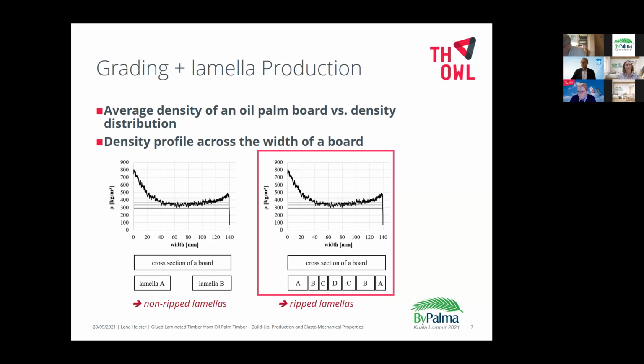trunk. In comparison to the conventional way of lamella production, you can see on the right the same density profile and the procedure of cutting strips as a function of the density gradient across the board cross-section. The calculated density limits to achieve a certain strength are shown here as gray horizontal lines. The cutting limits are located at the intersection between the smooth density profile and the density limit value. In contrast to the conventional method, strips with individual width and homogeneous density distribution across the cross-section are obtained. For further processing of GLT lamellas, strips with comparable densities are edge-glued together to edge-glued timber. The lamellas are then cut off the edge-glued timber as in the conventional method.